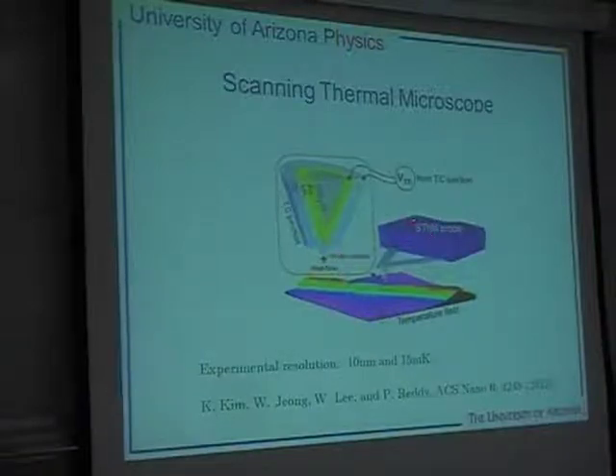And what they've made then is like an AFM cantilever, and on the tip of this cantilever they've mounted a nanoscale thermocouple. With this thermocouple, they can use it as a thermometer to measure temperature as a function of position. Of course, with scanning probe techniques you could obviously have a greater precision than 10 nanometers, but basically the limitation is that their coupling of this tip to the cantilever is about 700 thermal conductance quanta. So the only way they can actually see the sample is if they ram the tip into contact mode with the sample. And so the contact diameter is around 10 nanometers, so that is the spatial resolution of this thermometer. It's nothing fundamental, it's really just because they need to get better control of the thermal coupling to the environment so that they don't have to go into contact mode.